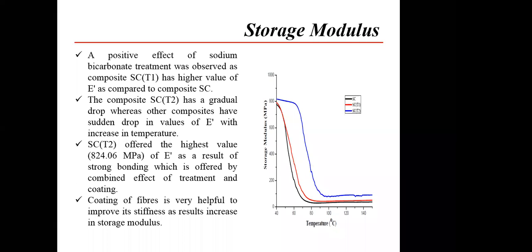And we can see the blue curve shown after the treatment, SCT2. This composite offers a good storage modulus as compared to the other two. So coating of the fiber is very useful to improve the stiffness as well as the storage capability. As a result, storage modulus increases.